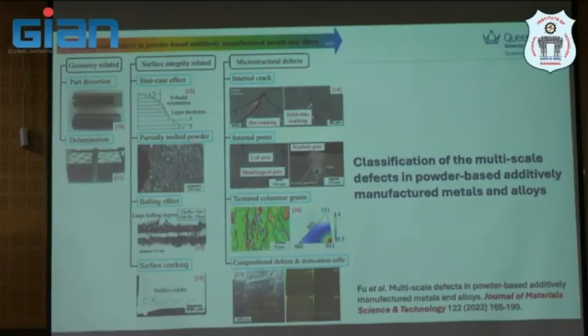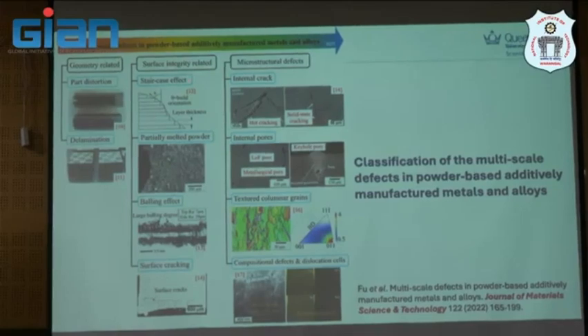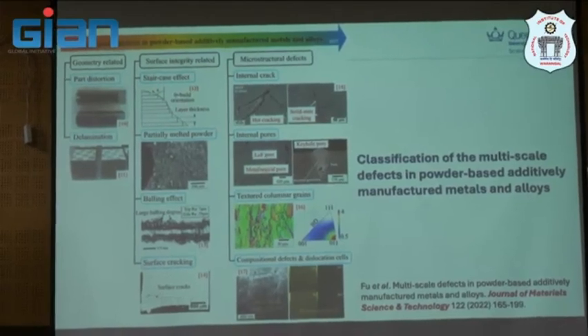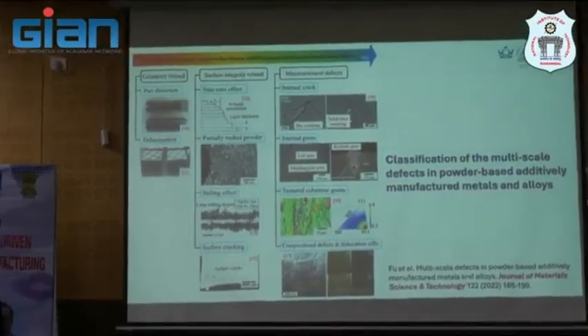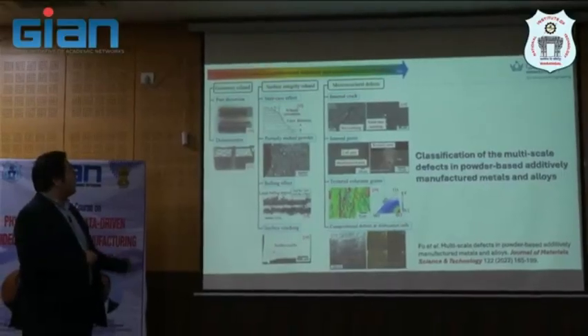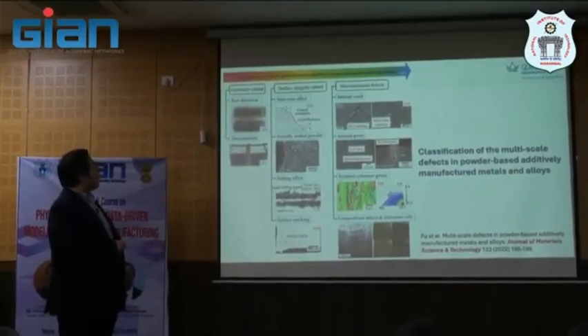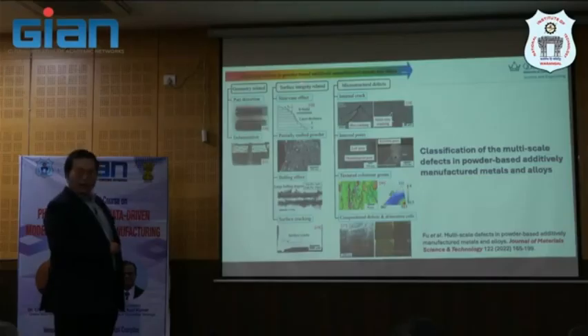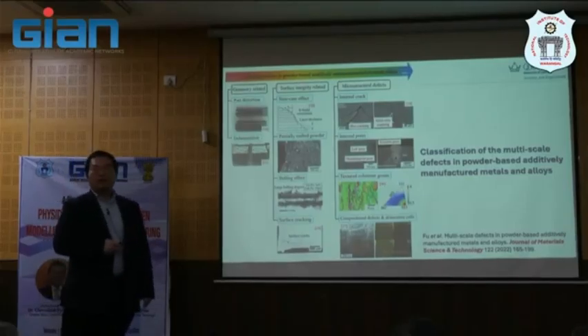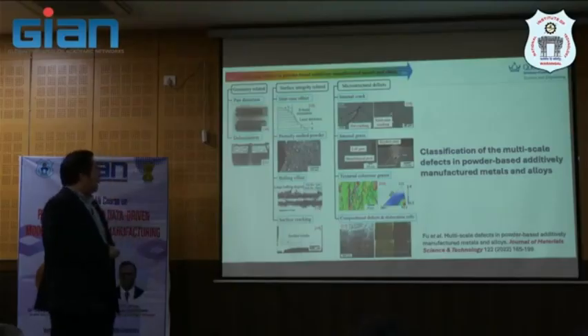up in the part. And another defect type is actually surface integrity related. So it's kind of staircase effect, probably somehow based on the geometry as well, but they focus more on the surface level, which is layer thickness. Or sometimes due to the melting, you get partially melted particles or powder. And then as melting progresses, as we discussed briefly in the previous few sessions, you'll get a balling effect, which is a surface tension phenomenon. That pretty much relates to during melting, or I would say the thermofluid interaction that we're talking about. And this is surface cracking.